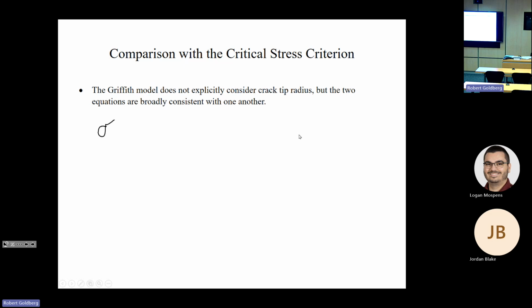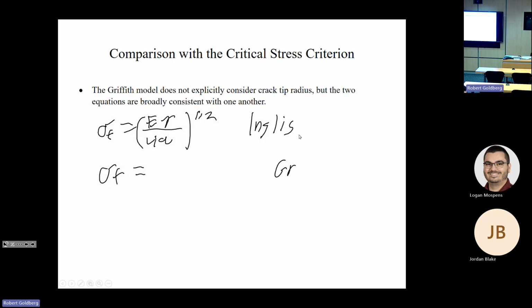So for the Inglis criteria, which was our maximum stress, we said that the failure stress was equal to the modulus times the surface energy divided by 4 times the half crack length to the 1/2 power, so the square root. And as we just derived with the Inglis, and as we just talked about for the Griffith, we have that the fracture stress for an infinitely sharp crack is 2 times the modulus times the surface energy divided by pi times the half crack length.